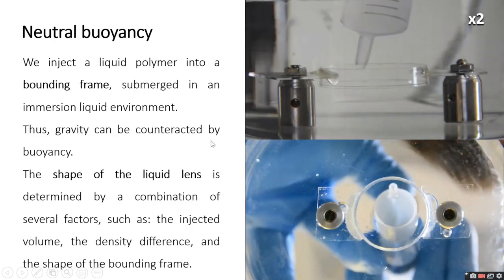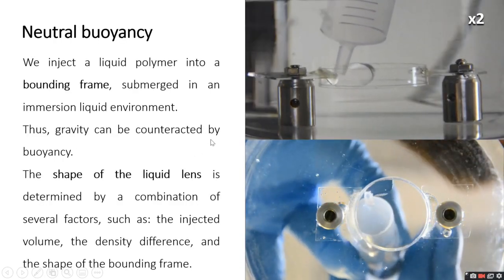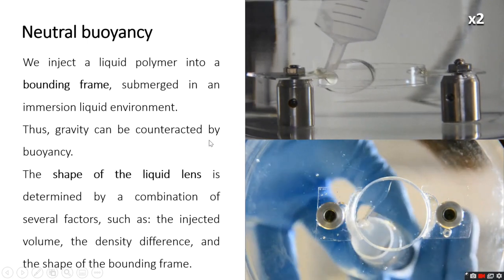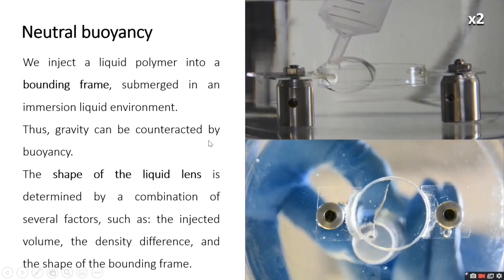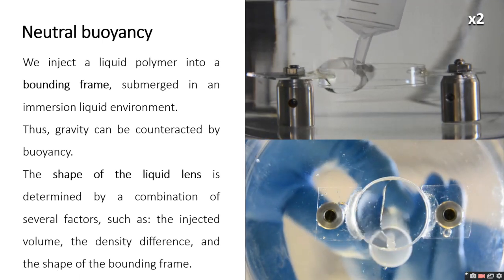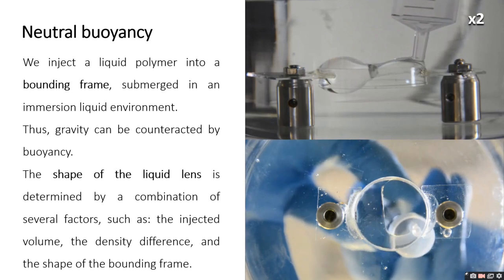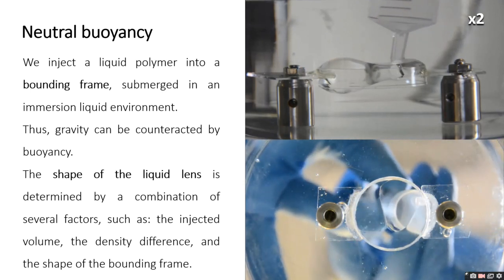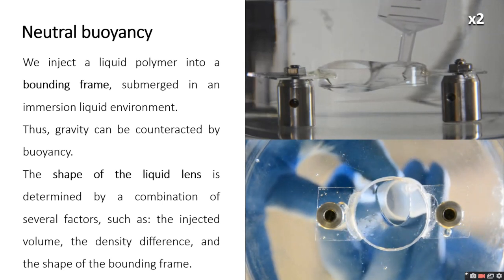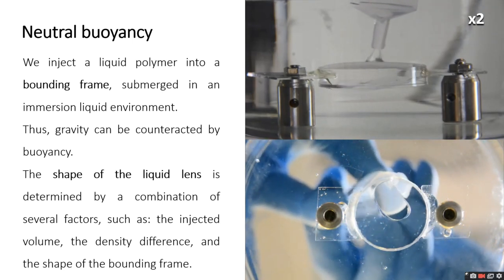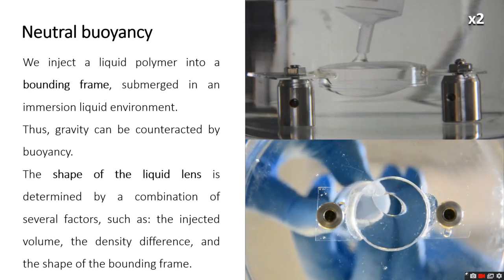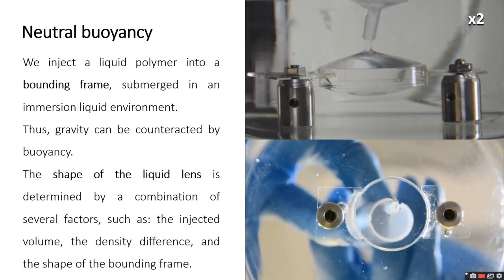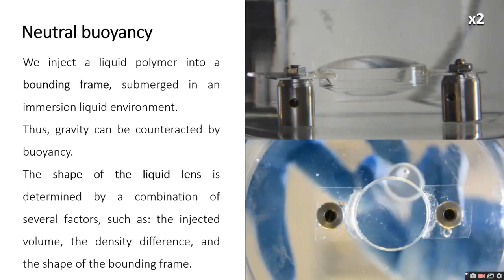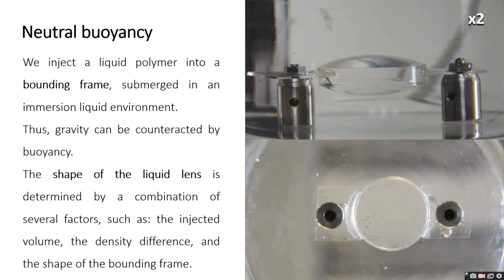In order to overcome gravity, we create our fluidic lenses inside an aquarium filled with an immiscible immersion liquid. By matching the density of the immersion liquid to that of the optical liquid, we create a microgravity environment where gravity is fully counteracted by buoyancy. Here you can see a video demonstrating manual injection of a simple 1-inch symmetric spherical lens. The curvature of the resulting lens is dictated by the injected volume. Adding more volume will increase the lens's curvature, while removing volume will decrease it. If the volume of the lens is taken to be smaller than the internal volume of the cylindrical bounding frame, then the optical liquid will form a concave lens with negative curvature.